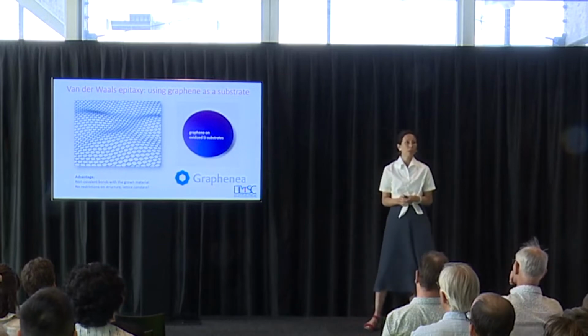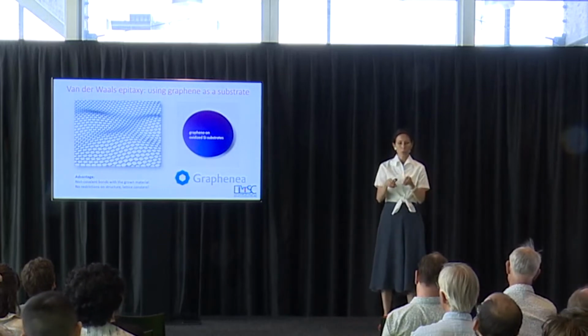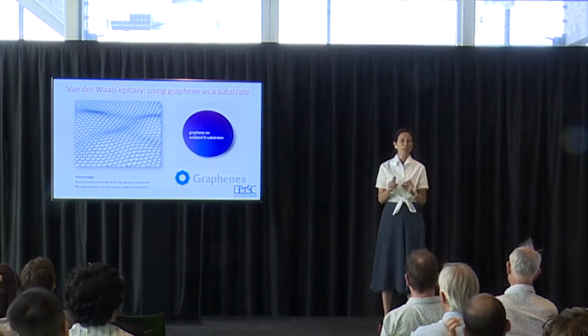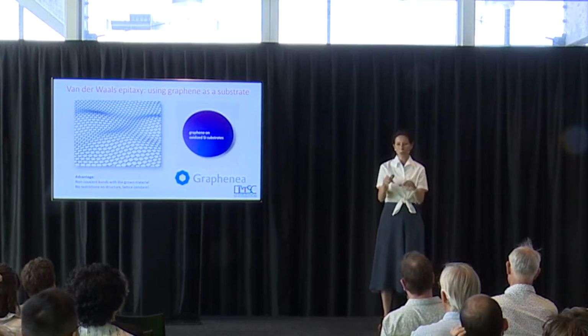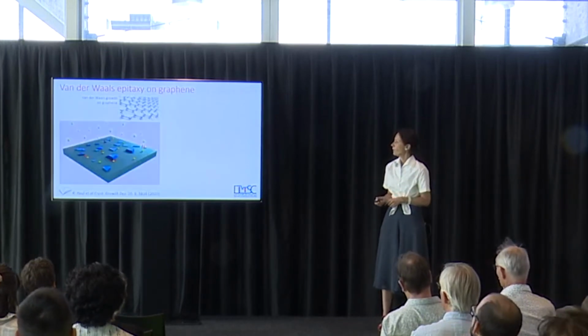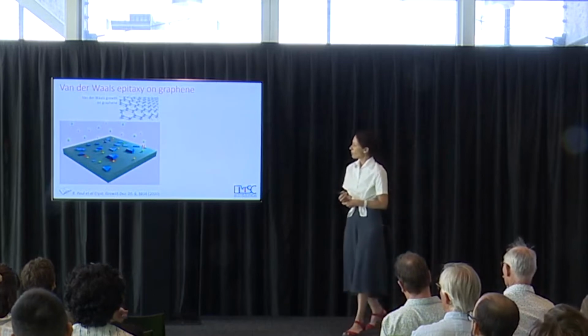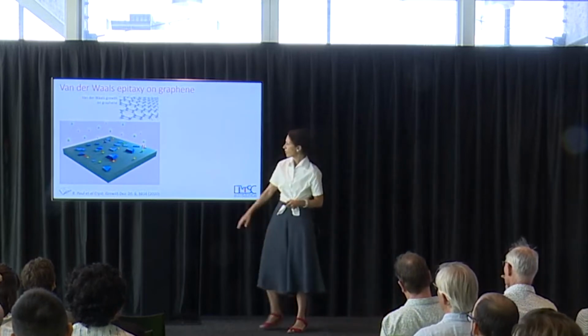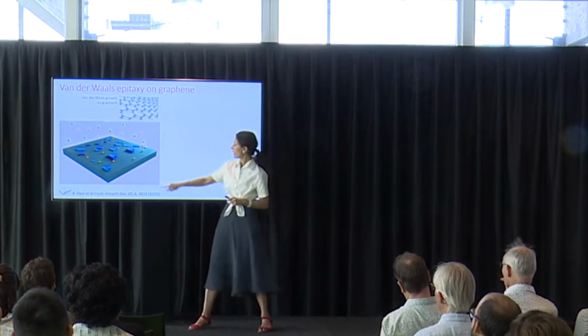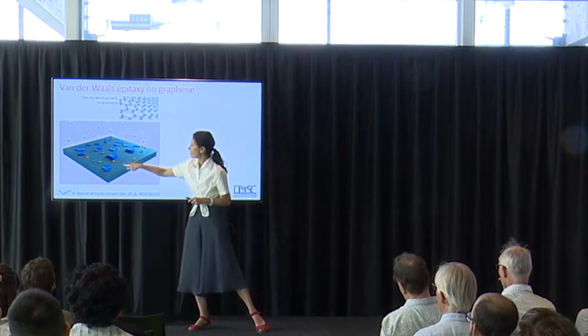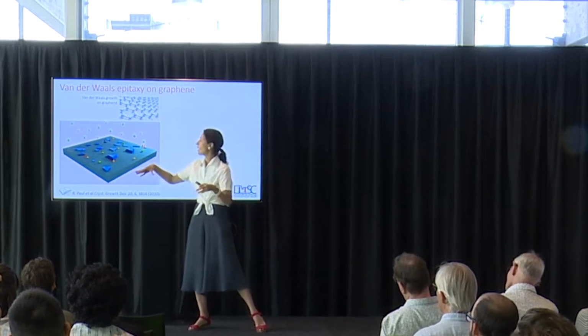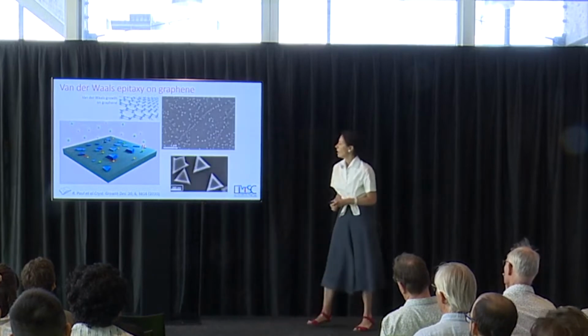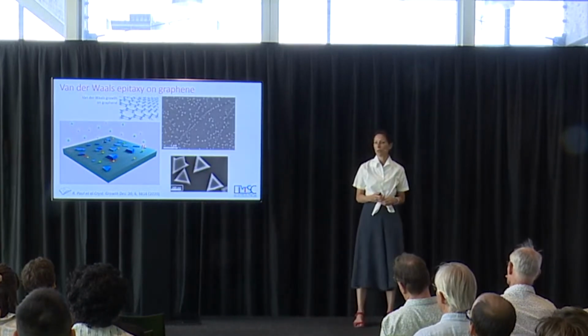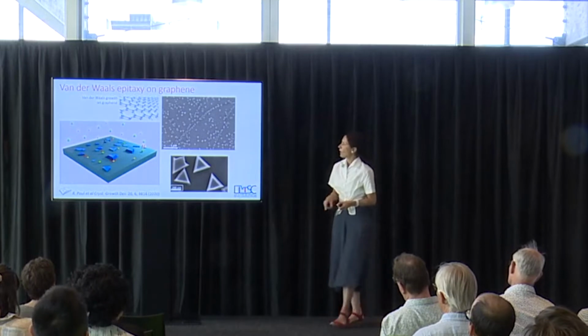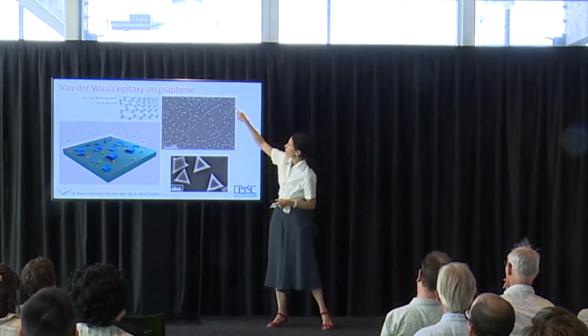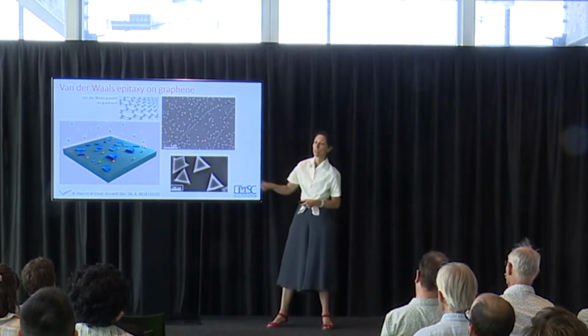So having a polycrystalline substrate allows you to have some very little density of defects, but enough that you can start nucleating a layer. So this is the mechanism we propose. You have a polycrystalline graphene substrate, and that has also some point defects, and so the atoms start sticking here, and then from this they create an island that evolves. And this is some scanning electron micrographs that show this. You can see very well the grain boundaries that are decorated by the initial stages of growth.